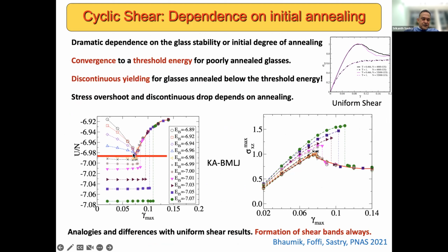Okay, so what one finds when one starts with very high energy or poorly annealed glasses is the behavior that I already indicated, which is that the energies of these glasses, with an increase in the strain amplitude, go to lower and lower values till they hit the yielding point, and then they go on to higher values beyond the yielding point. And the curious thing is, regardless of which initial energy over a certain range I start with, I always converge to this asymptotic energy before I yield. Okay, so this is already very interesting.